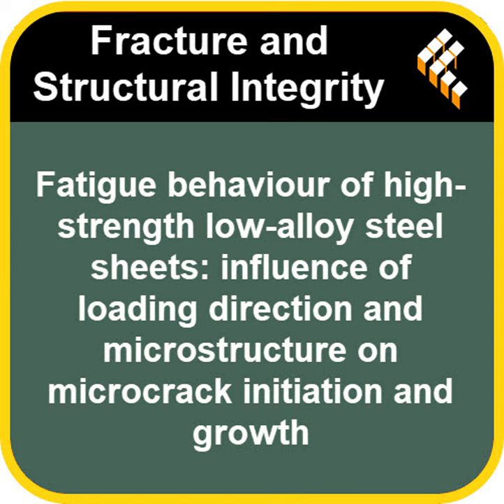Okay, so when they first tested its basic strength, just pulling it until it breaks, what did they find? Anything surprising there, especially with those different directions? Well, this is one of the first interesting bits. You might expect that because the material is rolled and has a texture, it would be stronger or weaker depending on which way you pull it. Yeah, definitely. But this HSLA 420 showed surprisingly little directional dependence, at least in its static properties. Whether they pulled it along the rolling direction, across it, or diagonally, the strength and ductility were pretty much the same. The yield stress ratio between RD and TD, for instance, was about 0.9.